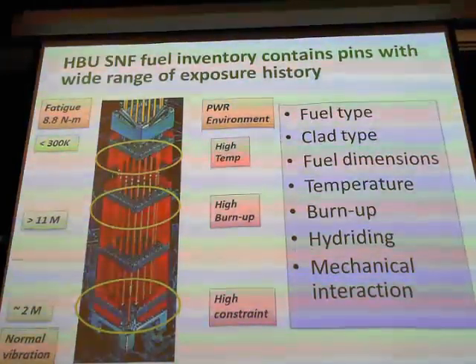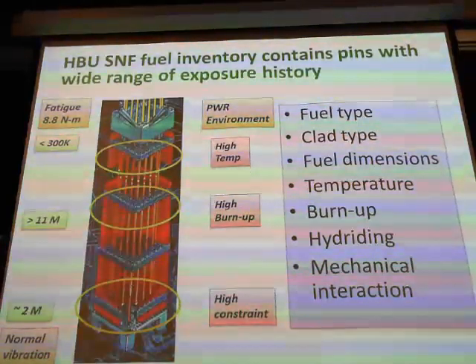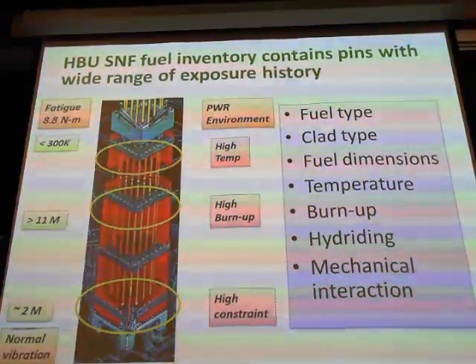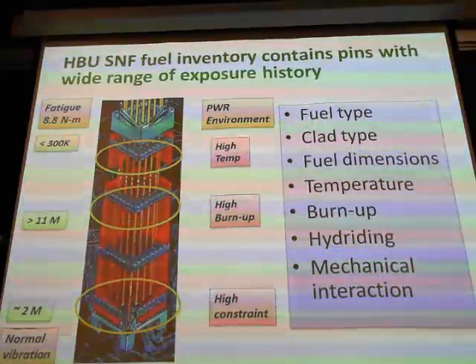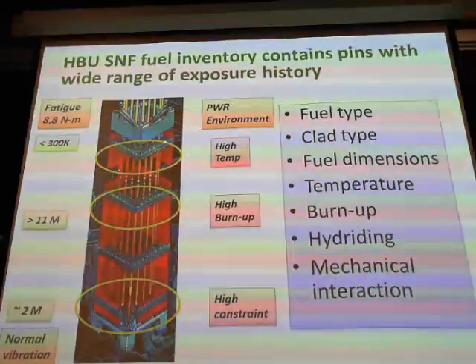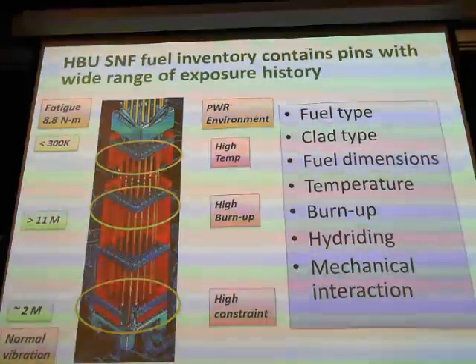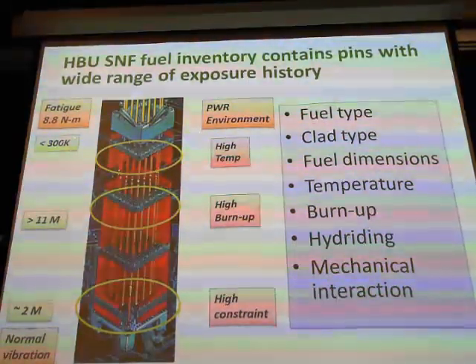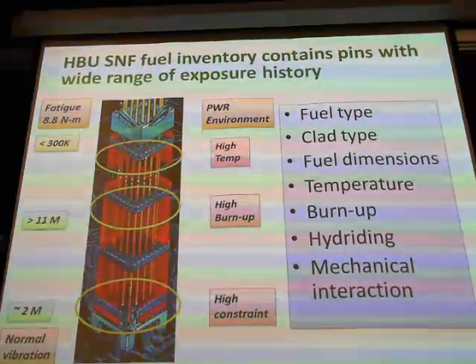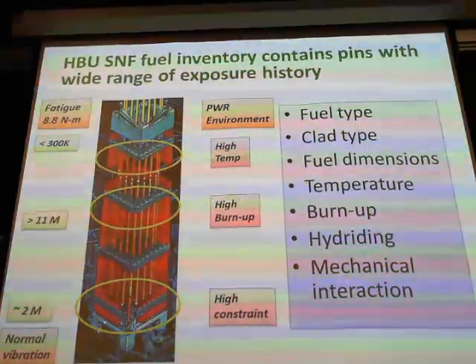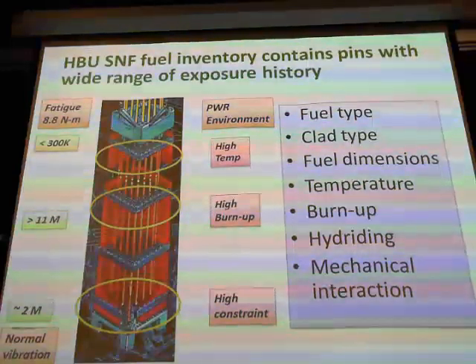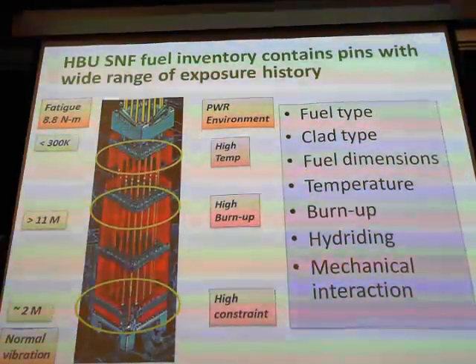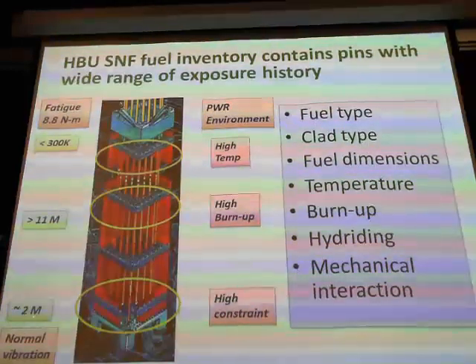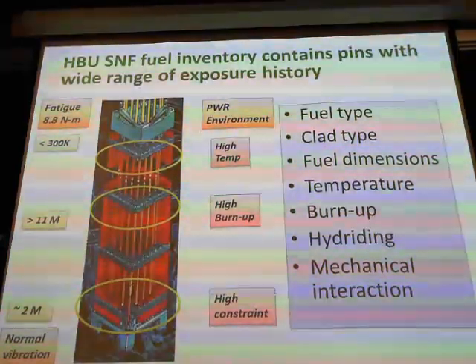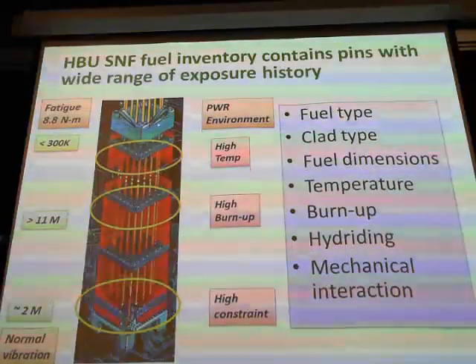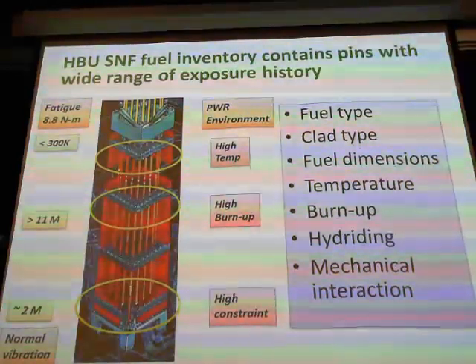So no way you can have transportation from the US across the continent reach 11 million cycles. So from this perspective, fuel is okay. But you look at here, this is higher temperature, which means more hydride. This one failed at less than 300 thousand cycles. And this one down here has a low irradiation dose and a slightly cooler temperature, and at 2 million cycles it failed. So your boundary condition, your surface environment, your constraint all affect your material performance.